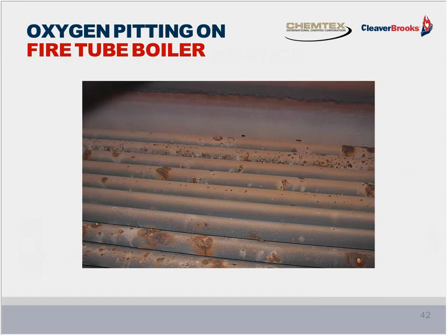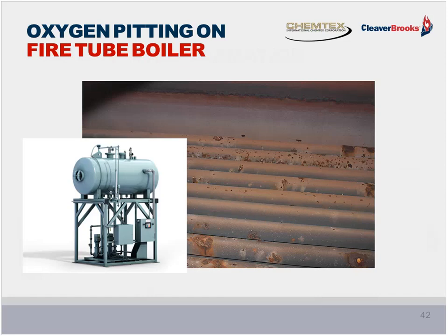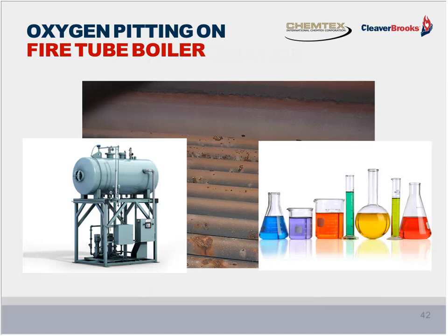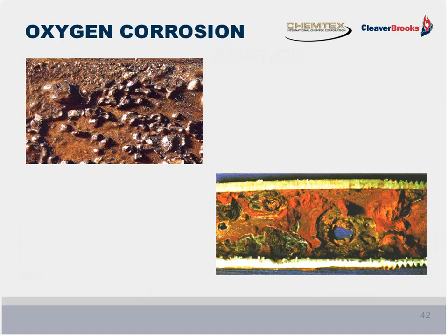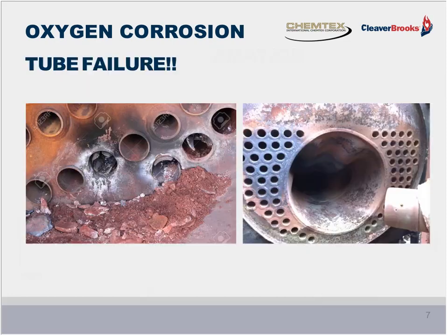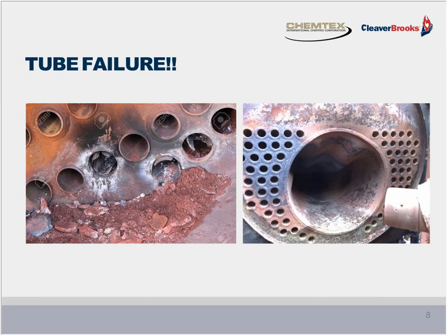The best answer? Well, again, it is a two-part approach with a deaerator to remove oxygen and carbon dioxide, and of course, chemicals to clean up the aftermath or any residuals that would be remaining. Because if you don't address the corrosive gas problem, this is what we have to contend with. And if we don't properly address the scale formers, this is what we get.